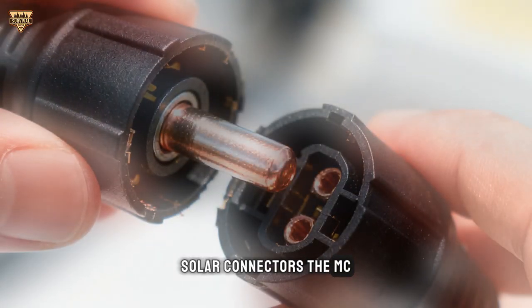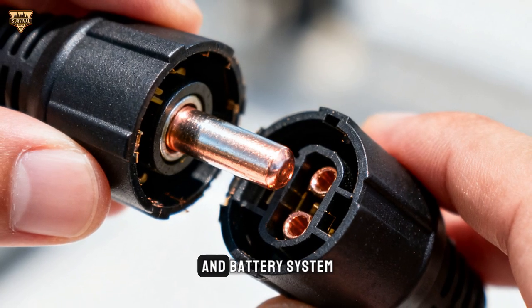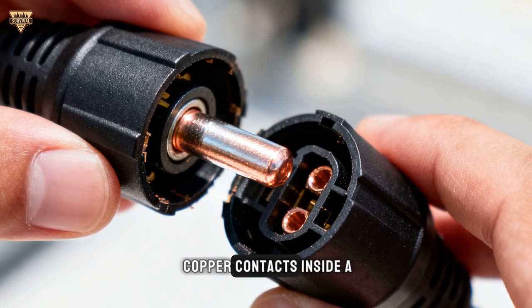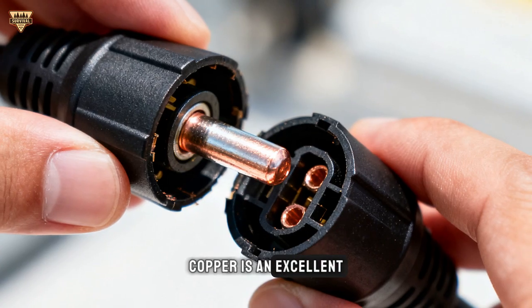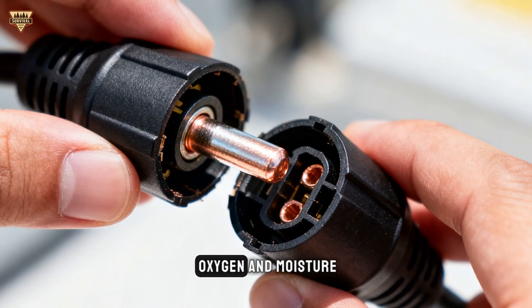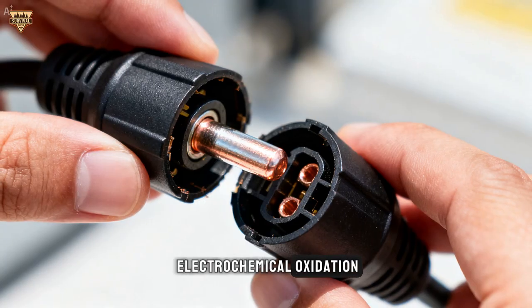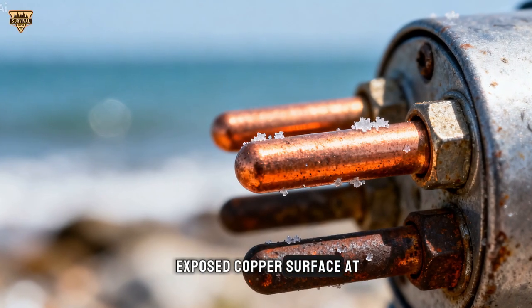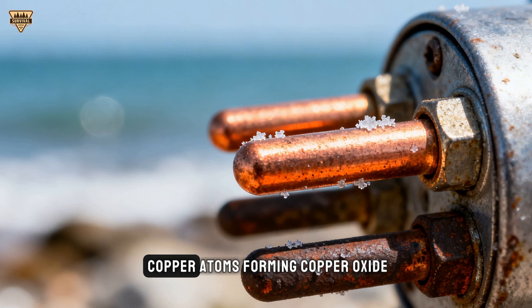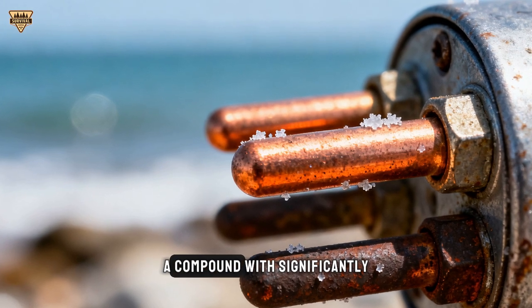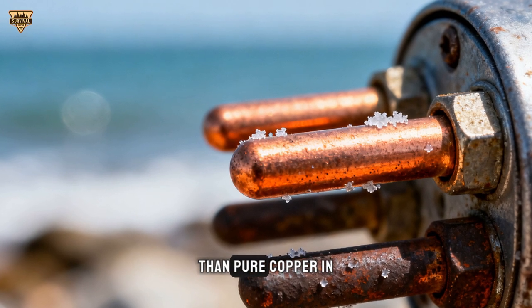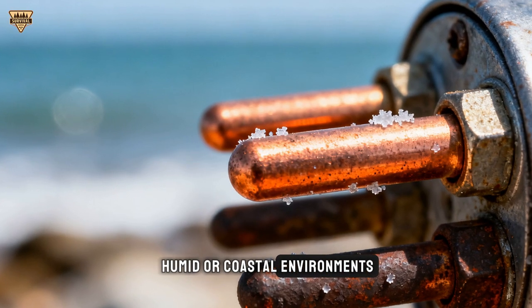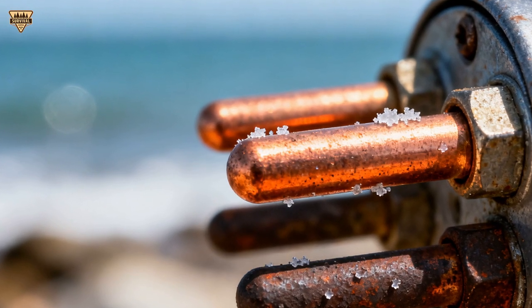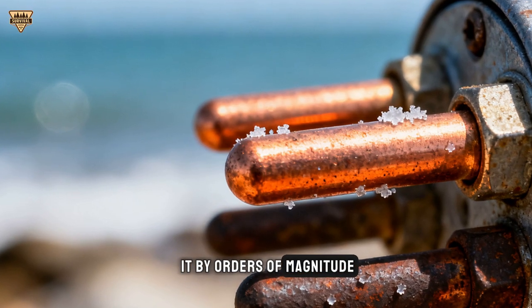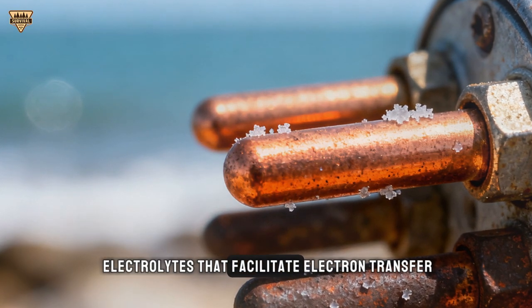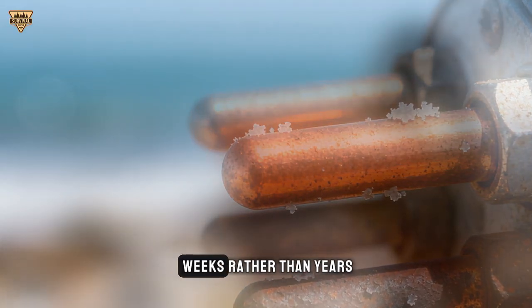Solar connectors, the MC4 plugs that connect your panels to your charge controller and battery system, are made of tinned copper contacts inside a polymer housing. Copper is an excellent electrical conductor, but reacts readily with oxygen and moisture through a process called electrochemical oxidation. When oxygen contacts the exposed copper surface at connector pins, it strips electrons from copper atoms, forming copper oxide, a compound with significantly higher electrical resistance than pure copper. In humid or coastal environments, moisture accelerates this reaction dramatically. Salt air environments accelerate it by orders of magnitude. Chloride ions act as electrolytes that facilitate electron transfer, making oxidation happen in weeks rather than years.